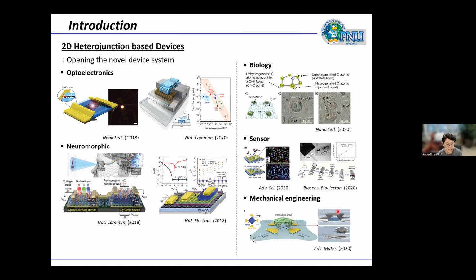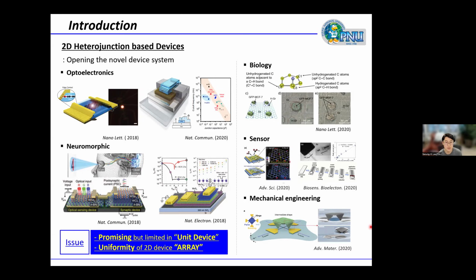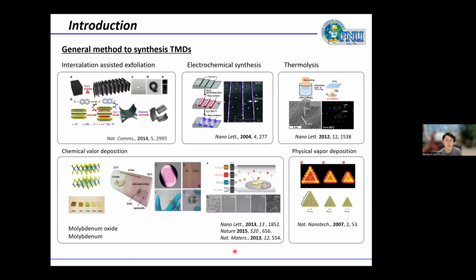From an industrial perspective, uniformity is more important than peak performance. Devices fabricated at different times must exhibit consistent characteristics. Although this may seem simple, it remains a challenge. In this work, I focus on identifying the root cause of this issue from the perspective of material synthesis. So here I summarize the five general preparation methods for transition metal dichalcogenides. Among these, three methods are the most widely used: chemical exfoliation, thermolysis, and chemical vapor deposition.